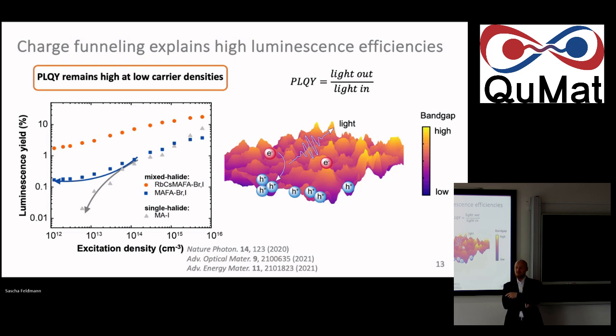So basically what's really going on is that we shuttle the carriers from a higher density to a lower density of traps region. If I accumulate lots of holes here where there's a lower hole trap density, then it's a useful thing. If it wouldn't affect that, then it's just a redistribution. We wouldn't globally win anything. But that's fortunately the case for perovskites, so it does help you.